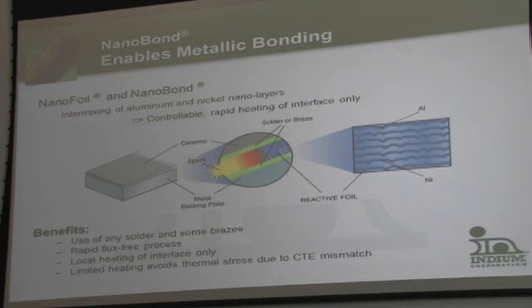You bond them together either by heating the whole thing up, and maybe using some kind of brazing or soldering process, or you can use something like this, where just at the point where the two materials touch, you can apply local, extremely high temperatures that then dissipate very rapidly because there's a very small amount of heat energy there. And so you get local heating of the interface. And one of the key things is that you don't get the thermal stresses. I mentioned earlier some of the thermal stresses that can be caused in chips. A lot of other types of applications may also be subject to thermal stresses. So because you don't have a problem with CTE mismatch, because you're not heating the whole thing up, just the interface, you get around a lot of these problems with residual thermal stresses.